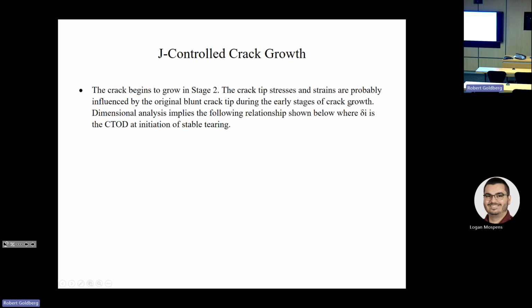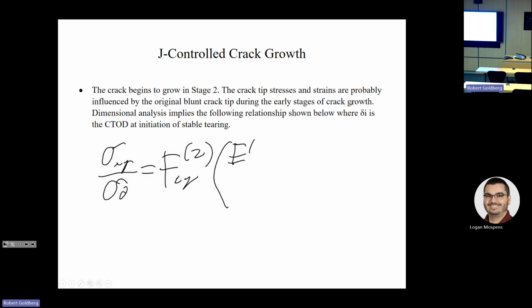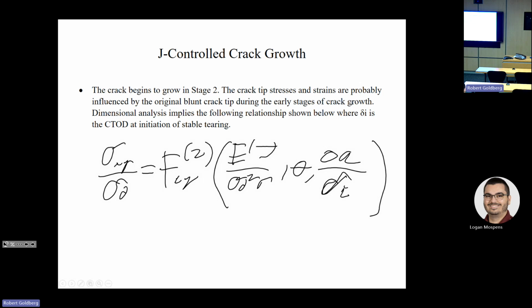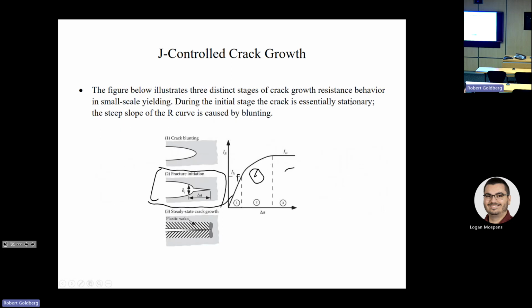So the crack stresses and strains are influenced a little bit by the original crack tip behavior, by the early stages of crack growth. But we can say that at the start of stable tearing, our stress divided by our yield stress is equal to a function valid for region 2, a function of E prime J over sigma naught squared R and theta, but it's also now a function of our change in crack length divided by our crack tip opening displacement. And then finally, we're going to look at zone 3, where we have just steady state crack growth.